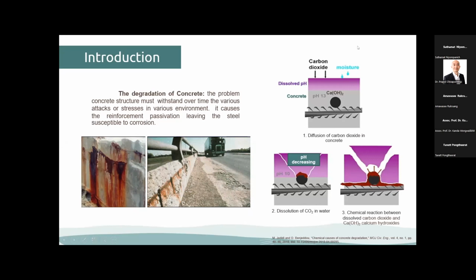Concrete structures must withstand violent actions and stresses over time. This leads to reinforcement passivation, leaving the steel susceptible to corrosion. The carbon dioxide in the air forms an acid solution in a moist environment, which can react with the hydrated cement paste and neutralize the alkalinity of the concrete. Carbonation has a significant impact on the corrosion of the steel and affects the degradation of the concrete.